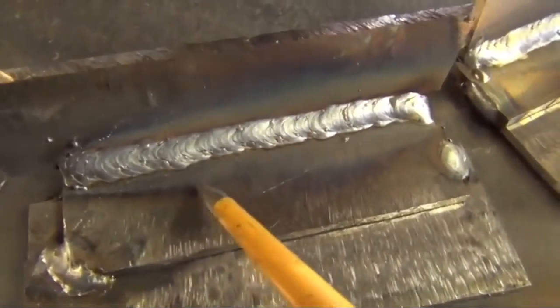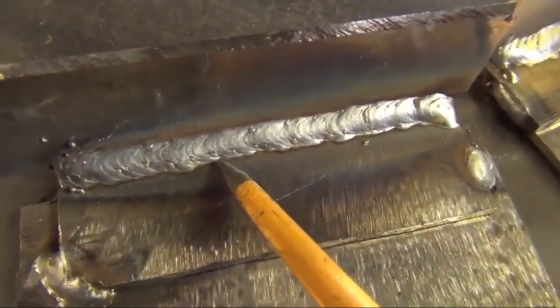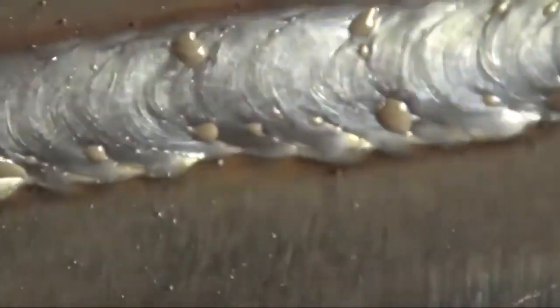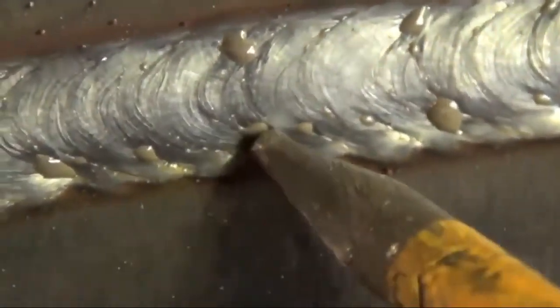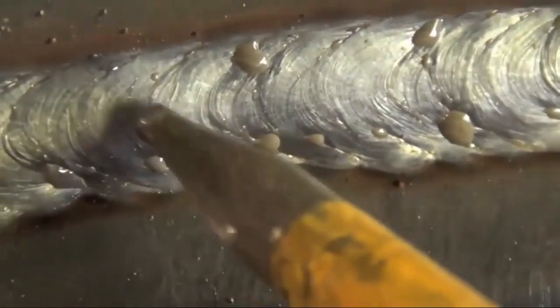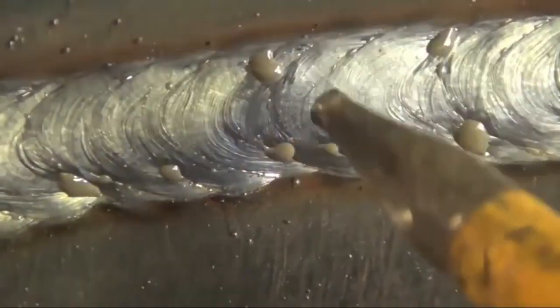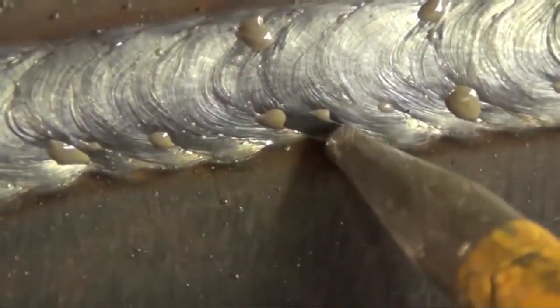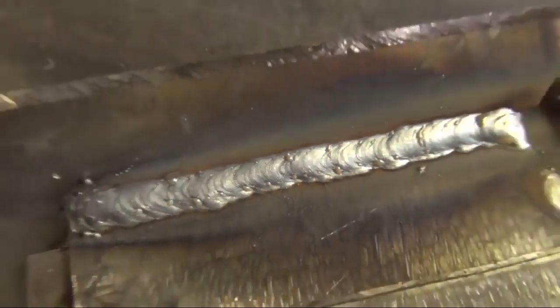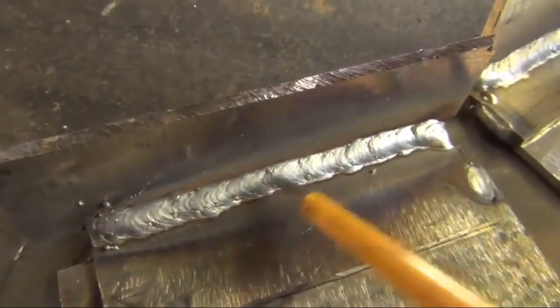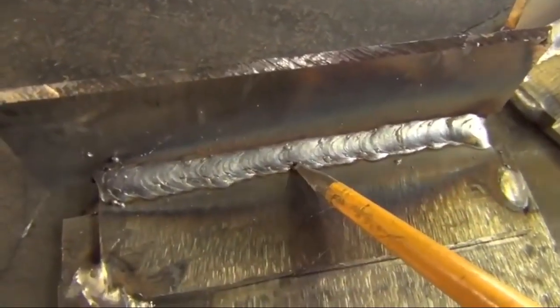If you're not consistent, you get little divots like that one right there. I don't know how well you guys can see that, but that is what's called a lack of fusion. This is caused by me just welding along and then missing that spot, and there's a little notch, and if there was ever a lot of force placed upon this joint, that's probably where the weld would start to fail. So that's bad. You don't want to do that.